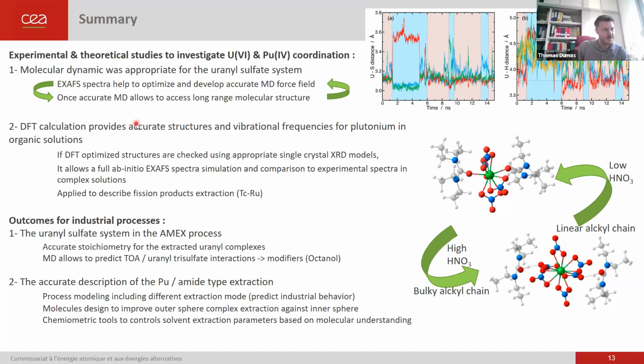DFT works well also in organic phase. It is something that you have to check by comparison with XRD model, because there are other systems where it doesn't work. And there are several outcomes for industrial processes, like for the Amex process, we know now the stoichiometry of the complex. We are trying to look at some modifier they add in the industrial case. And we have a better description of what is going on with the amide type extraction system.